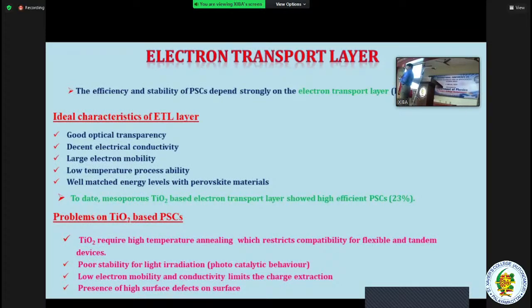When you use titanium oxide as the ETL layer structure, we are able to get an efficiency of 23%. But at the same time, the stability of the perovskite solar cell based on the titanium oxide ETL layer will not be sufficient. All the properties get depleted. So, next slide.